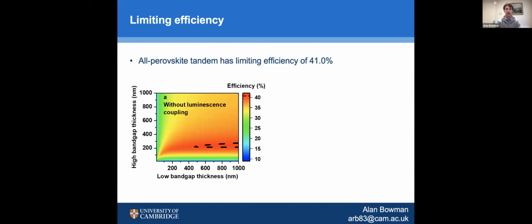If I put all that together, then I can come out with this figure quite readily that the limiting efficiency of a halide perovskite is 41%. What I'm showing here is the limiting efficiency as I vary the thickness of this red and green layer, the low bandgap and the high bandgap layer. And you can see that to get this 41%, you've got to be very specific with your design criteria. You have to be in this very small region of thicknesses, which is quite tricky to do experimentally.